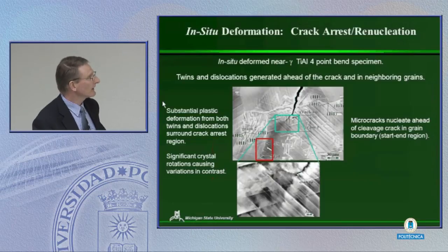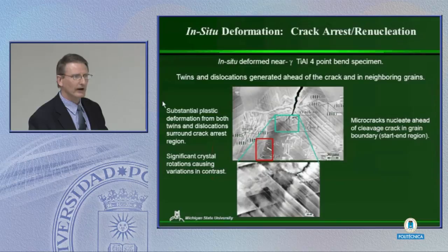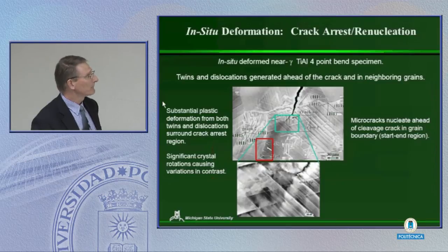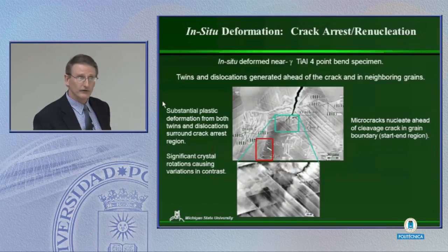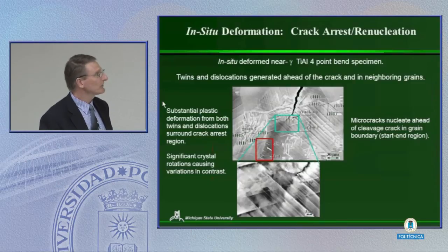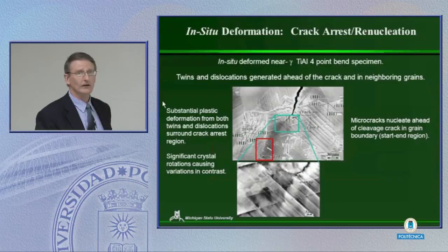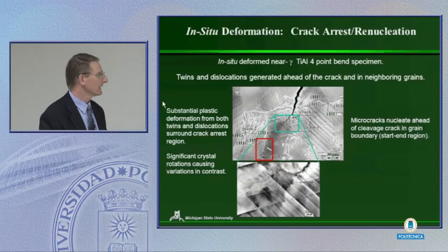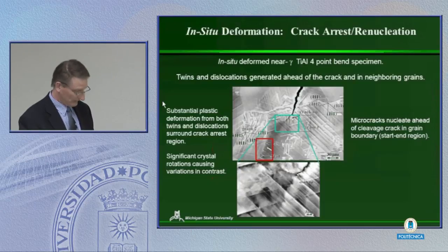Okay? So if I look at that crack tip in some more detail, we can see there's actually a lot of deformation going on here. We can see that there are lots of deformation twins. If we look closely here, we see kind of a rough, or what I would call mottled, background, which suggests we have lots of dislocations there, and they're really difficult to resolve at this point. Because we know the true orientations of all these grains, we can now do trace analysis to identify the specific planes. And with those specific planes, we know that there's a specific twin direction. So we know all the crystallographic details of these deformation twins. We know exactly what twins they are, rather than just saying we have a twin on a given plane. And that's going to become useful for us here in just a second.